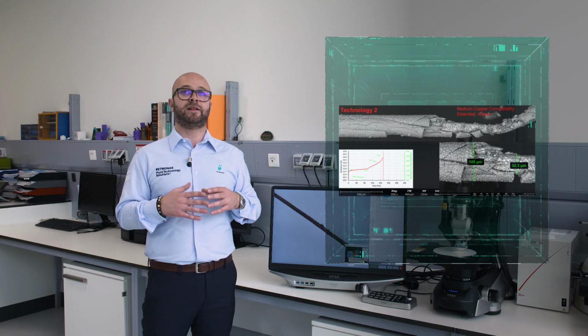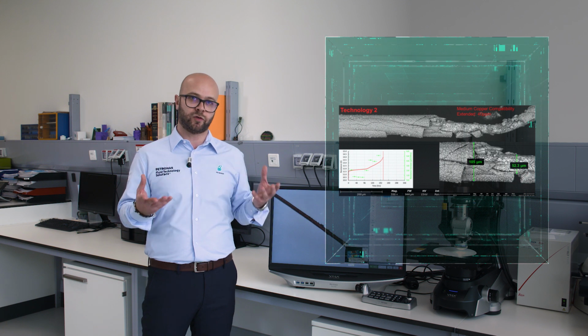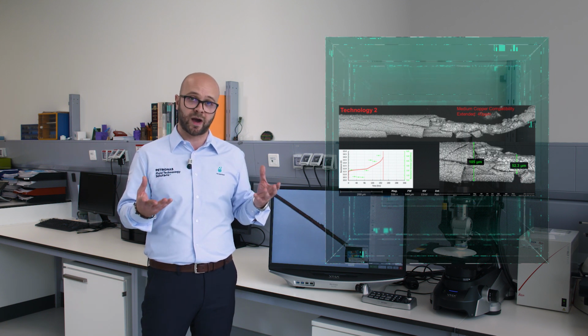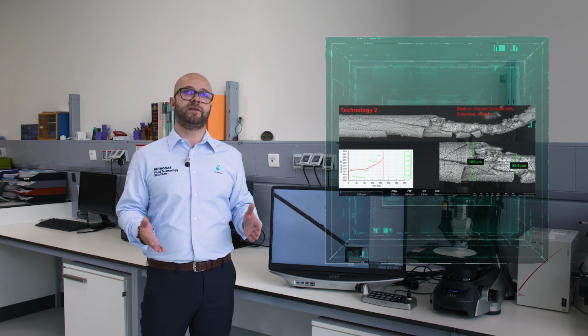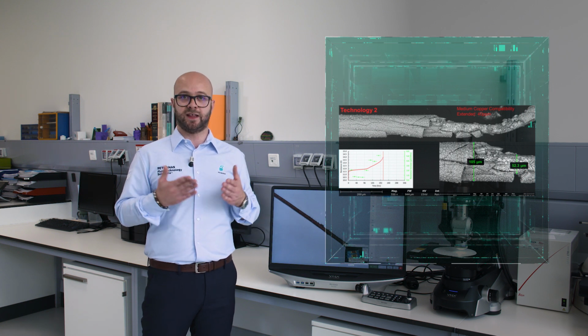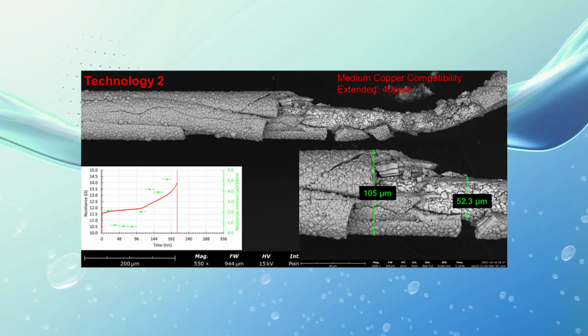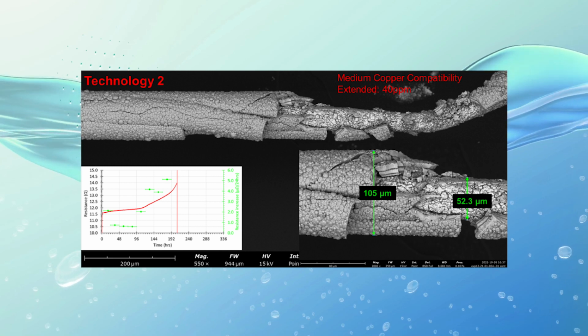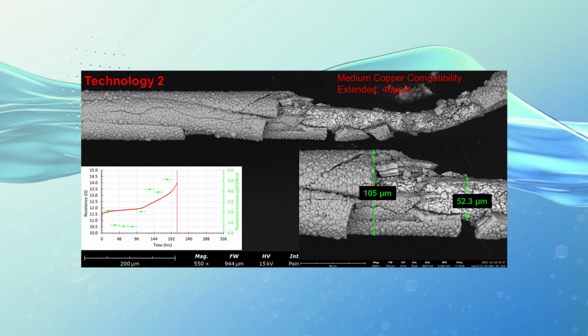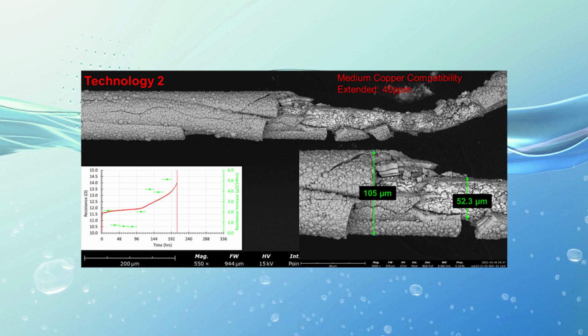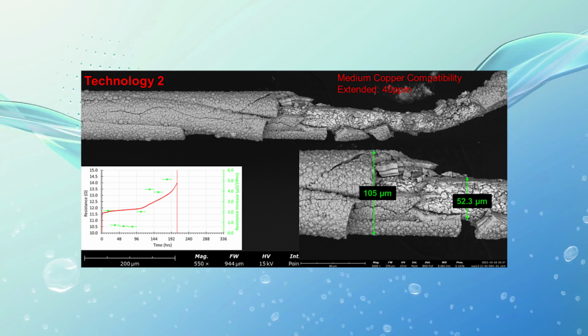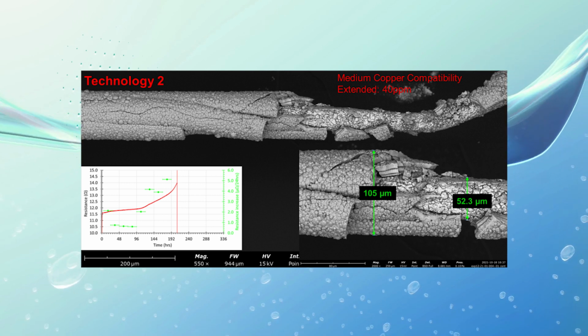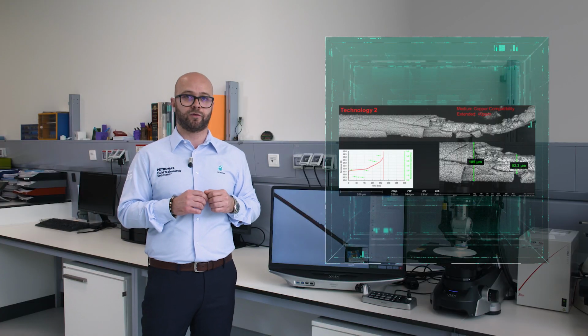This suggests that we have a continuous dissolution of the wire, releasing copper that is used to build up such thick layer. The breaking of the wire might be induced by two phenomena: the decrease of thickness of the wire itself and the increase of the mechanical strength due to the accumulation of the corrosion product on the wire surface.